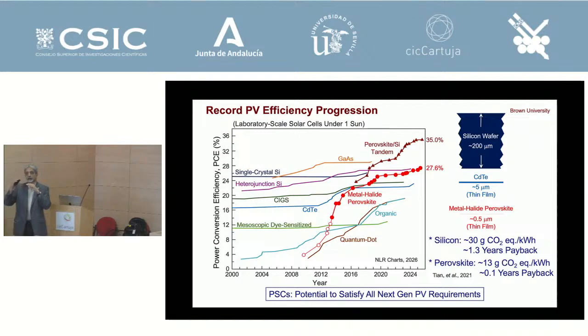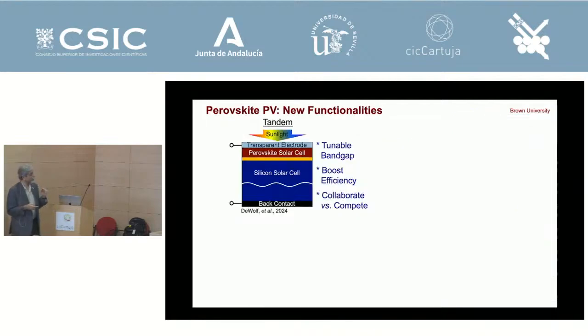But you can actually add this perovskite, which can be tuned in order to maximize the efficiency, right? So it can go up to 35%, right? And so with the new technology, you're not just replacing old technology. By virtue of these new materials and new technology, you have new functionality. It's different. It's not exactly the same. It doesn't fit in the slot. It has its own new properties. And so you can use this for this tandem, as I mentioned, on top of silicon.